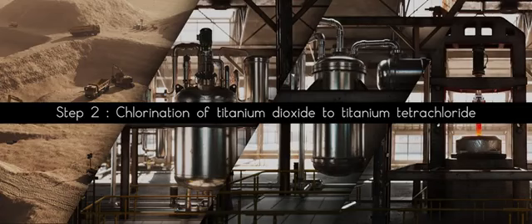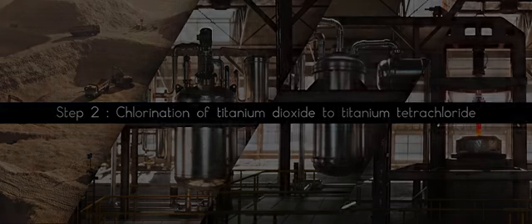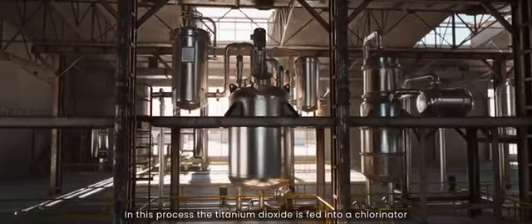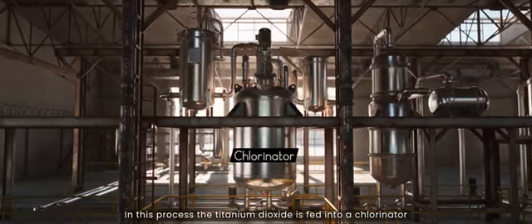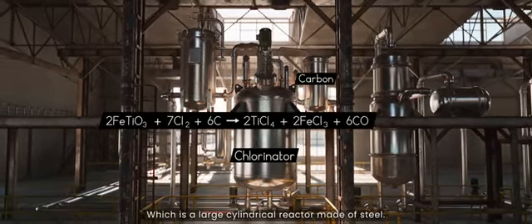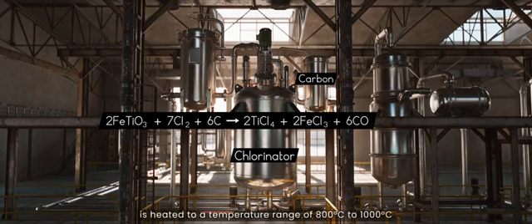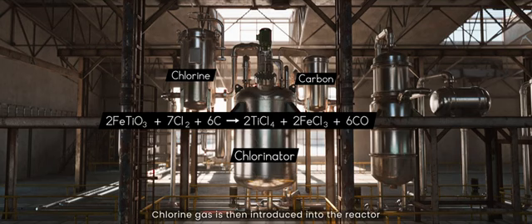Step 2. Chlorination of titanium dioxide to titanium tetrachloride. In this process, the titanium dioxide is fed into a chlorinator, which is a large cylindrical reactor made of steel, heated to a temperature range of 800 to 1000 degrees centigrade. Chlorine gas is then introduced into the reactor where it reacts with the titanium dioxide to produce titanium tetrachloride.